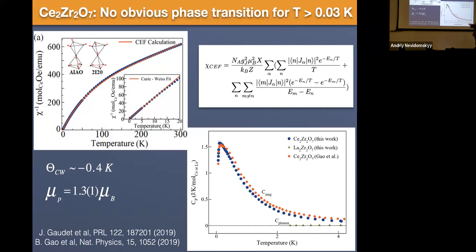For the susceptibility, you can see the data is in black, and it's curved, but there's no sharp features in it. And actually, the whole curve can be well understood on the basis of a Van Vleck susceptibility, which depends on you understanding the crystal field eigenstates and eigenvalues for cerium-3+, which we do, and I'll come to that in a minute. So that can be fully understood, and that's the red line. And then for the low temperature heat capacity, which is associated with the degrees of freedom of the J equals 5/2 at the cerium site, that's giving rise to the Schottky-like anomaly, but there's no phase transition, there's no lambda-like anomaly anywhere here, down to about 60 millikelvin.